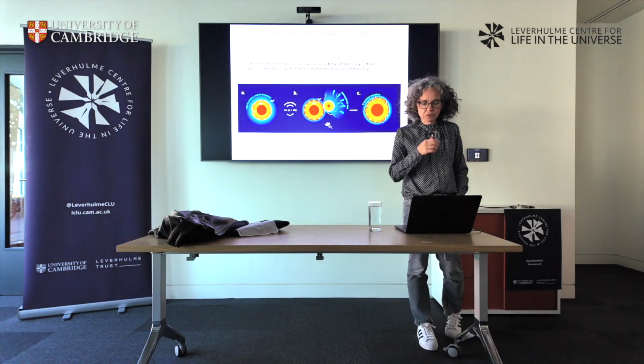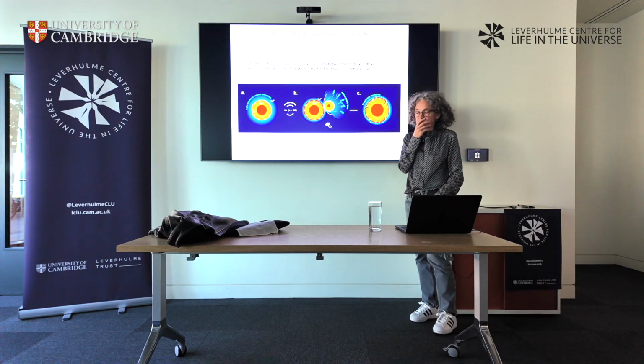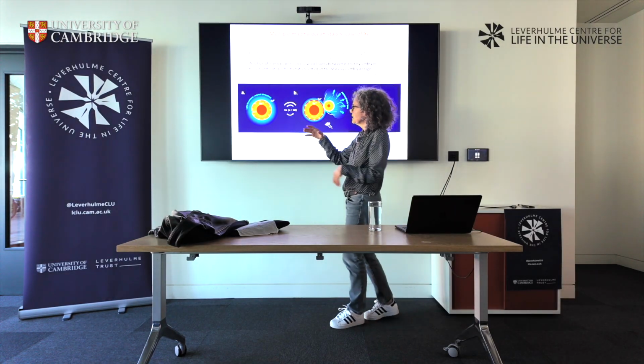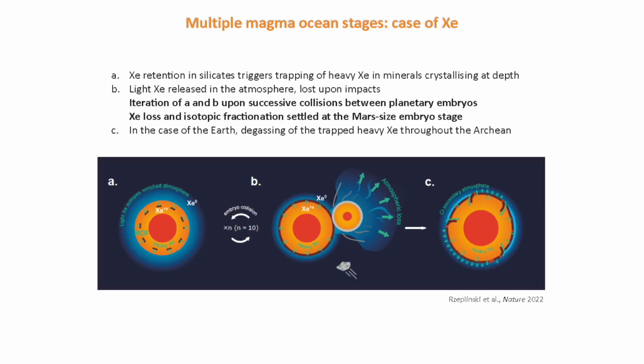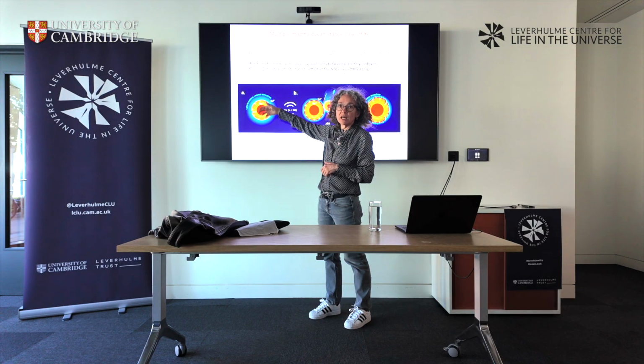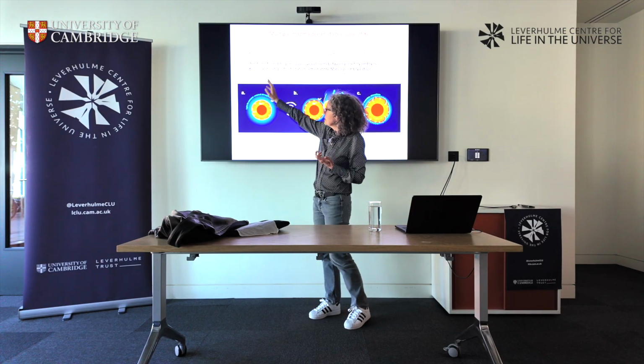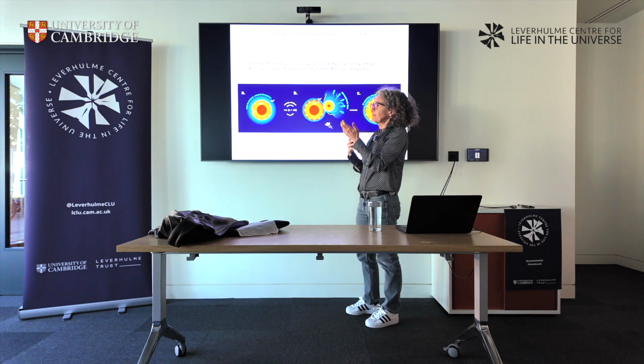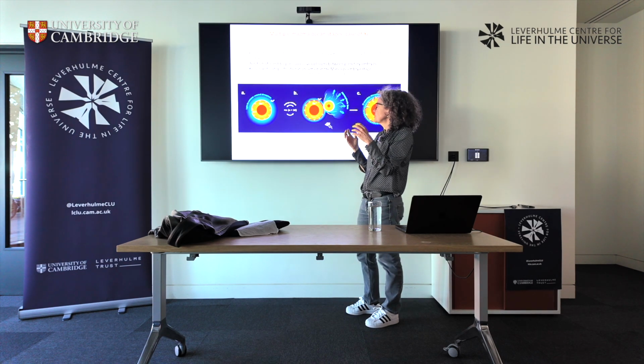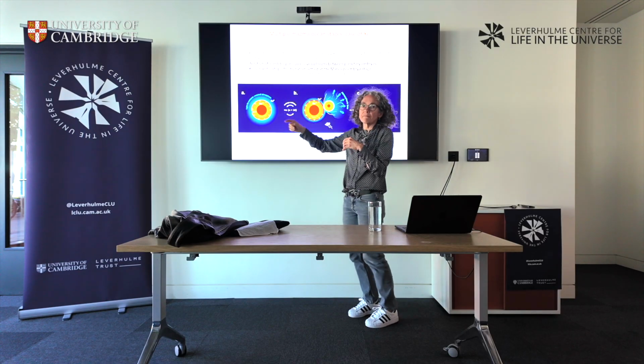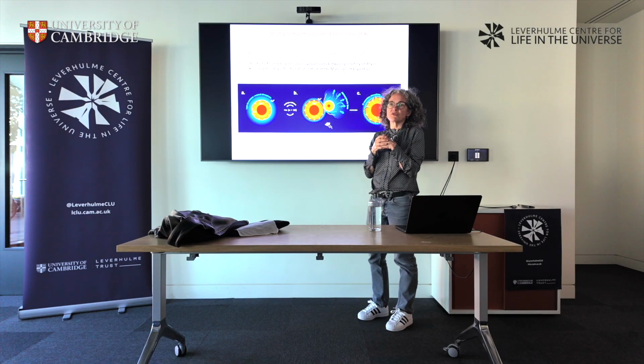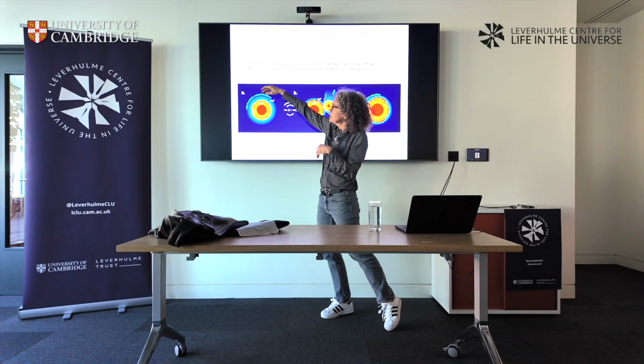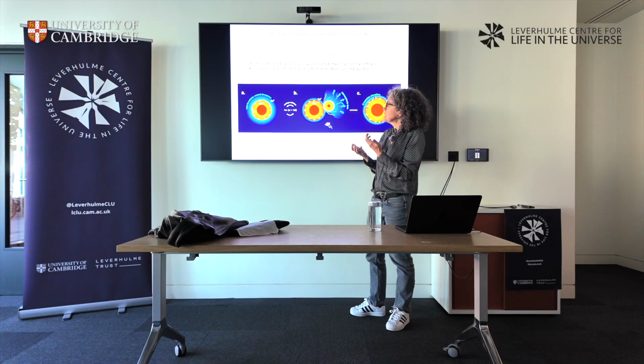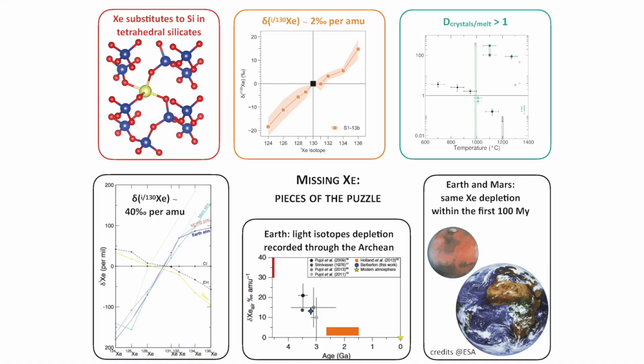Okay, so how do we reconcile this together? Well, that's the scenario we came to. You have these starting planetary embryos that are molten. Crystals form at depth, they trap xenon, and they trap the heavy isotopes. The light isotopes are preferentially released, get somehow into the atmosphere, and then you have an early solar system with lots of collisions between these bodies. Each time you have collisions, you lose the atmosphere. So you lose this light xenon isotope fraction. And if you repeat this about 10 times, then we can explain these numbers in terms of isotopic fractionation.